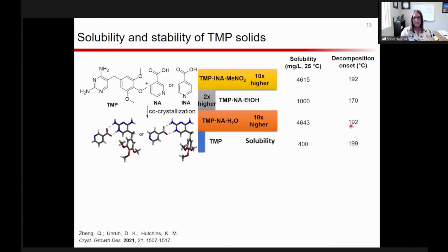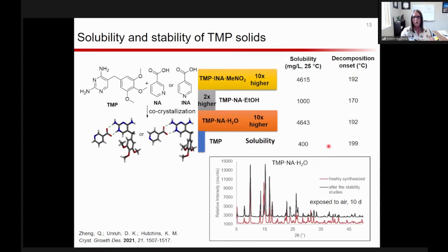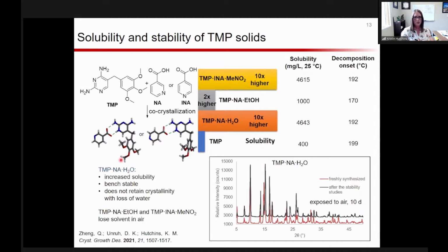And then with the nicotinic acid hydrate, we were also interested in confirming that if we just left this on the bench, whether it would retain crystallinity or lose water over time. So we synthesized it fresh, that's in red, and then set it on the bench for a period of 10 days, just exposed to air. And we could see that it was still incredibly crystalline. Powder X-ray diffraction correlated really nicely to the freshly synthesized sample. So that hydrate has increased solubility and is bench stable.